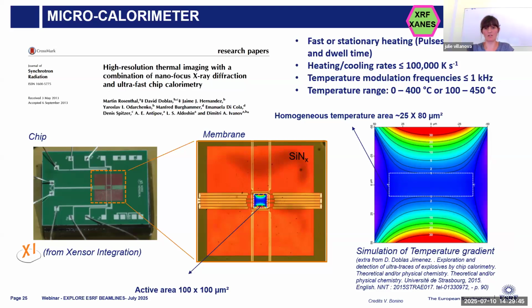Then the second sample environment that we can offer for the 2D scanning at the beamline is this microcalorimeter. It has first been used on ID13 with nano-focus X-ray diffraction, and we can also use it at ID16B. So here you have a picture of the chip, which is a commercial one. This chip has an active area of 100 by 100 microns. So it means that it's better to prepare the sample before the beam time in order to be able to place the sample in the active area using, for example, a micromanipulator, knowing that according to some simulation, the homogeneous temperature area is a bit smaller. And then this device can be used in order to heat up the sample from 0 to 400, 450 degrees, either using a ramp and stationary heating, or we can also apply a fast heating in a pulse mode, let's say.